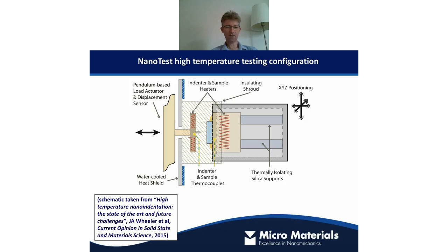How we achieve this ability to test at very high temperature accurately is done by having independent heating of both the sample and the indenter. And this dual heating, if you like, allows us to have a localized hot zone, and that localized hot zone allows us to do measurements without thermal drift. But otherwise, what you find, and what our competitors find essentially, is that they get large amounts of thermal drift that make the results unreliable. So you need to have this isothermal contact zone, which we've got in this patented hot stage shown here.